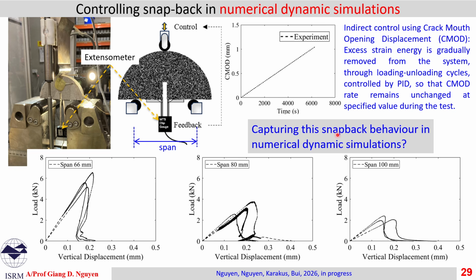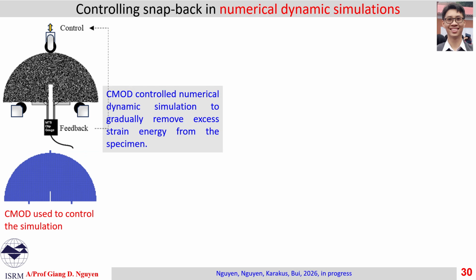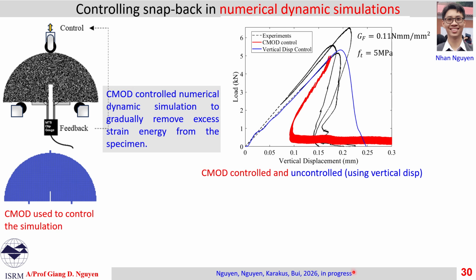The question here is whether this kind of snapback can be captured in our numerical dynamic simulation. Dynamic here means we don't remove the acceleration in the governing equation, and this is even more challenging than capturing this under quasi-static conditions. So we apply the same principle, using crack opening displacement to control the simulation. The details will come in one of our papers to be submitted soon. So the results are quite promising.